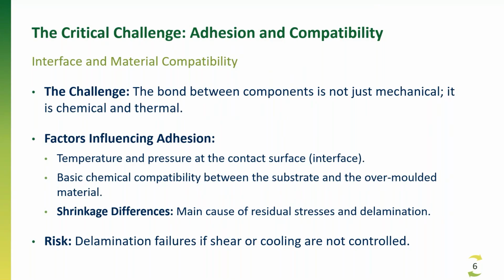And we also have to take into account the shrinkage differences. What I mean with this is that we are going to have 2 materials at 2 different temperatures, and that might mean that before the epoxy resin is properly cured in the bond between both materials, we are going to suffer a lot of stress, and we are going to put this interlaminate or laminate material that will bond in a critical condition, okay? Because we will have one material shrinking at one point and the other at another, so we can suffer delamination points.